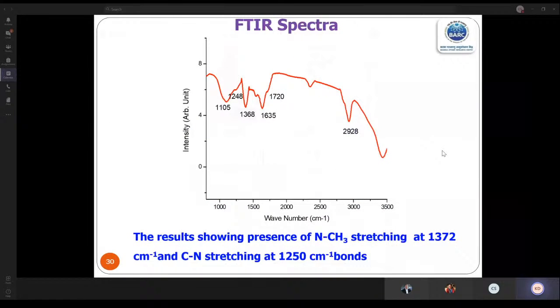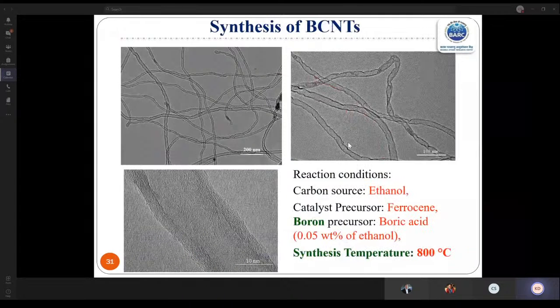So how can we characterize nitrogen doping? Apart from the bamboo shape structure, we can do FTIR, that is Fourier transform infrared spectroscopy, where we get typical bonding of nitrogen with CH3, nitrogen carbon bonding at various positions, from where we can conclude, okay, nitrogen has been doped. We have also tried boron doping.